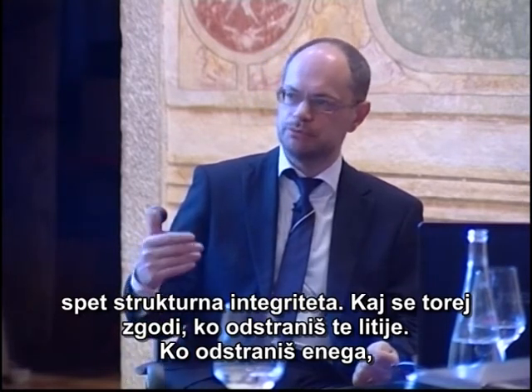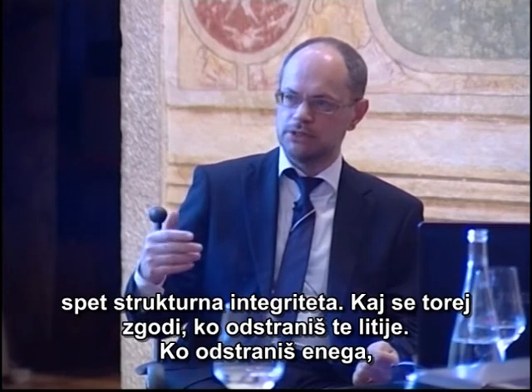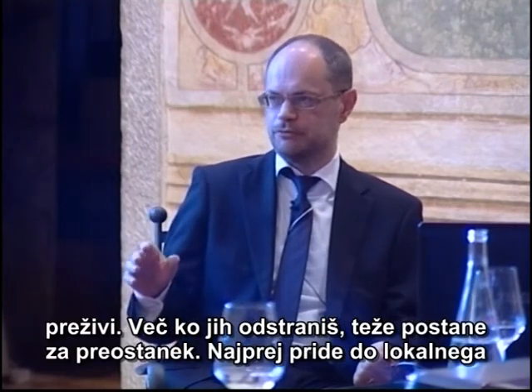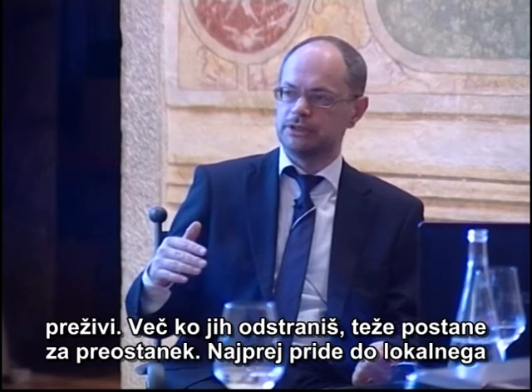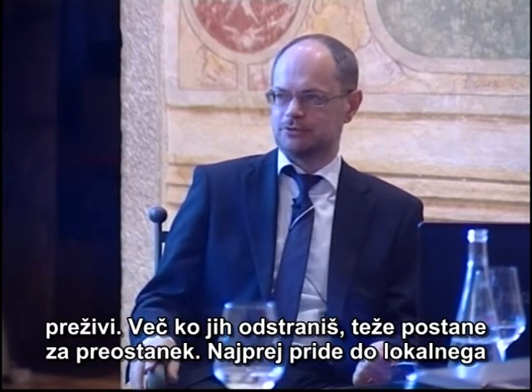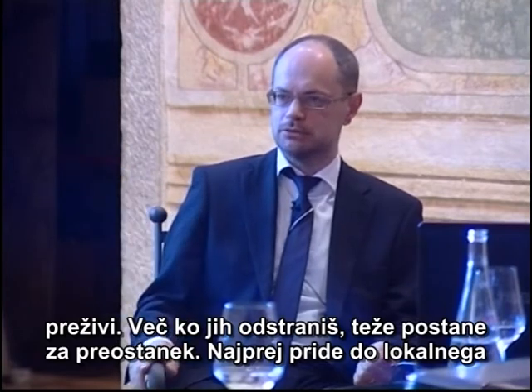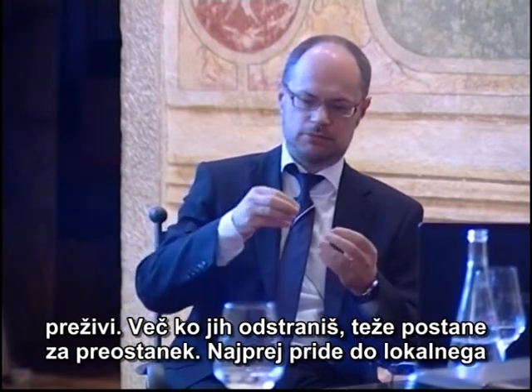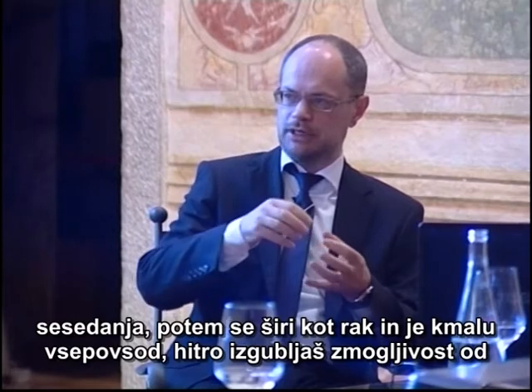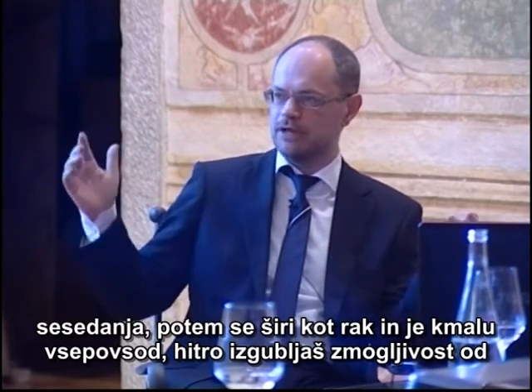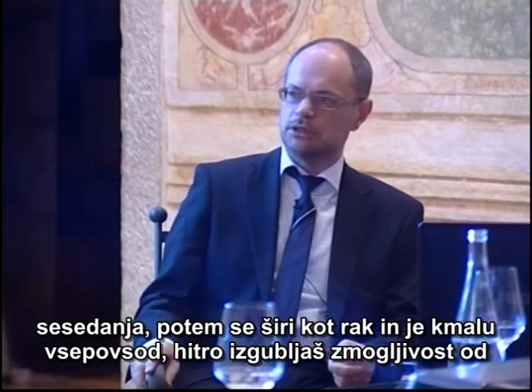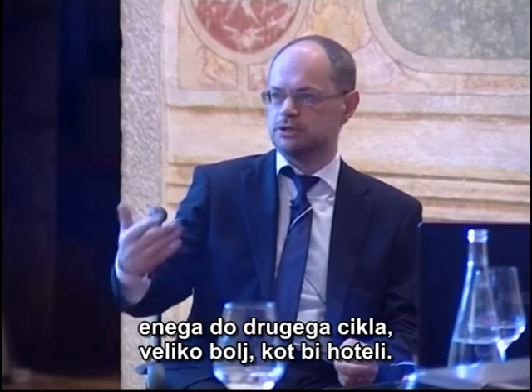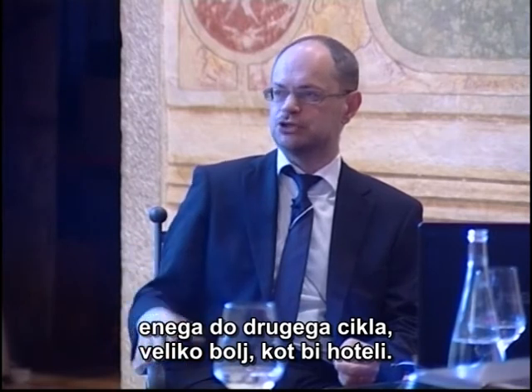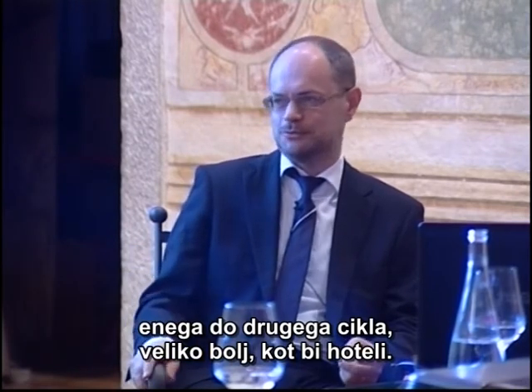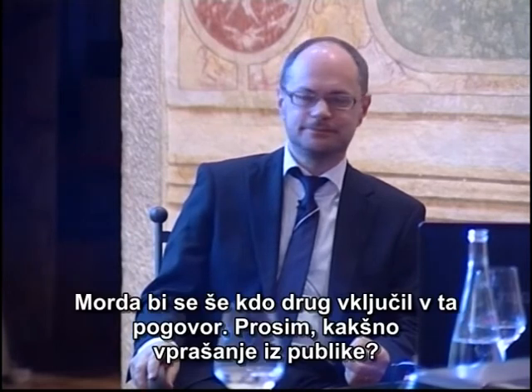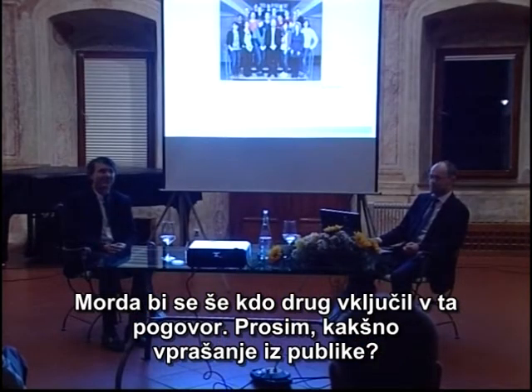So what happens when you remove these lithiums? If you remove 1 lithium, maybe it survives. If you remove more, the more you remove, the harder it gets for the rest. So you usually get some local collapses of the structure, and then it just spreads like a cancer everywhere else. So you really are losing your capacity from one cycle to another, and quite rapidly, much more than you want to.